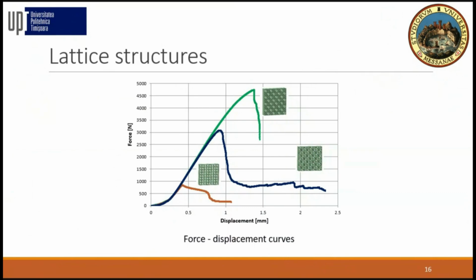These are some comparisons between these three structures. What we can see here, considering the energy, the area below the load-displacement curve, the lowest is from the square structure. Then we have higher for the triangular, and we can get this, let's say, typical load-displacement curve where we have a plateau for the cellular materials, and the third one is the sponge-inspired structure.